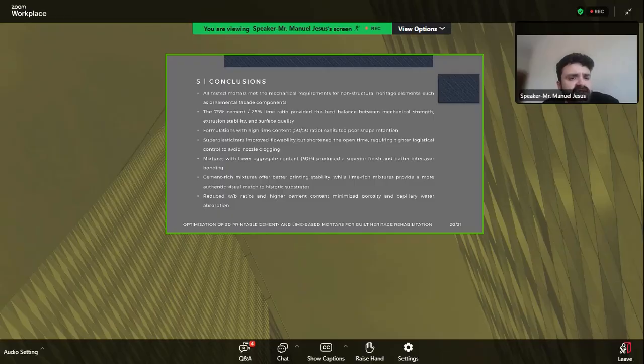So the conclusions that we could draw from this work are that the tested mortars met the mechanical requirements for non-structural heritage elements. The mortars with a higher cement ratio provided the best balance between mechanical strength, extrusion stability, and surface quality. The formulations with higher lime content exhibited poor shape retention. The superplasticizers improved the flowability but shortened the open time.